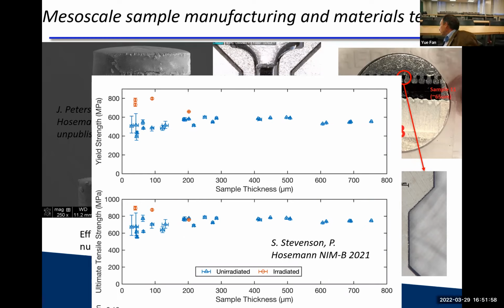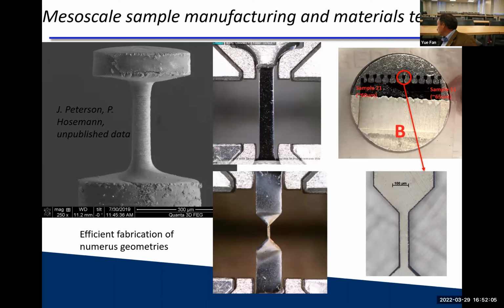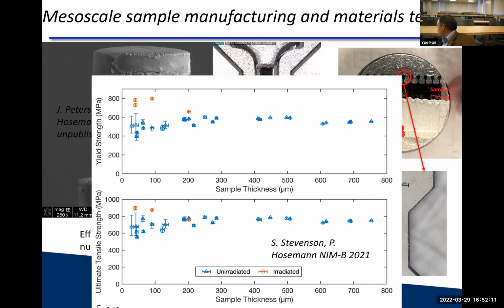And so yield strength versus sample thickness plotted, or ultimate tensile stress versus sample thickness, and those are basically those samples here, where they have different thicknesses and the same XY dimension, and we cut them thinner and thinner and try to understand that relationship. How far can I go this way and still get valid data out of it? And what we can see is that 30 MeV deuterons, a fraction of a dpa, actually did already change the property in this instance, right? So the yield stress is higher in the ion beam irradiated material, but at the same dimension. So that's where it's heading at this point.